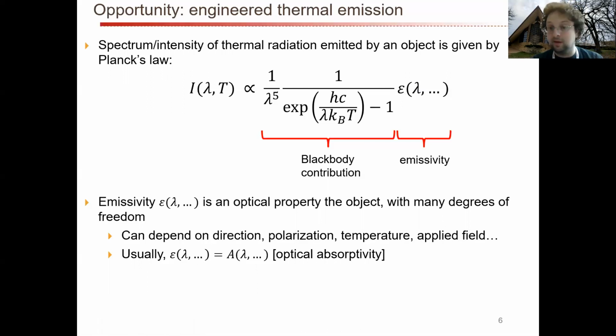You can imagine thermal emitters that emit only in one direction, that emit only a narrow range of wavelengths, that emit only polarized light, and so forth and so forth. And usually the way that we think about engineering these things is actually by engineering the optical absorptivity as a function of these parameters, because according to a thermodynamic statement called Kirchhoff's law of thermal radiation, the emissivity, which is again a function of all these parameters, is precisely equal to the optical absorptivity. So this is very, very widely used, this Kirchhoff's law of thermal radiation.